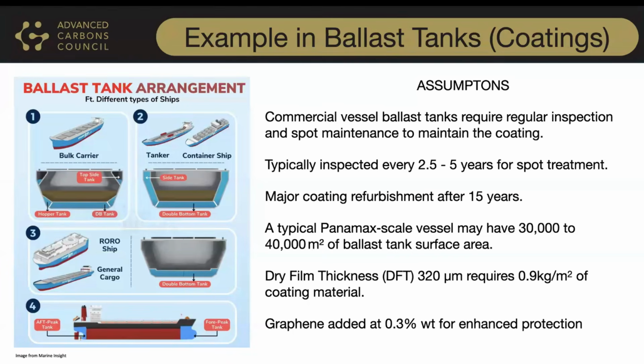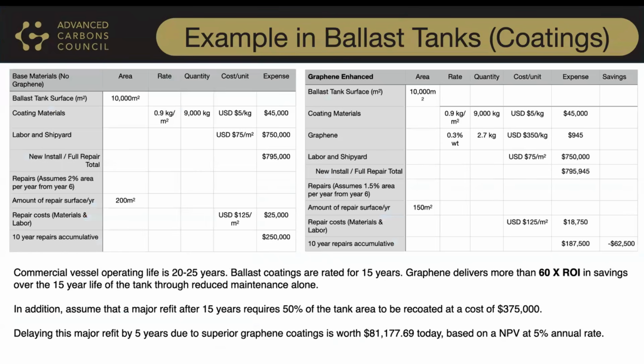And if you have a typical Panamax, and that just means the largest vessel that could go through the Panama Canal prior to the enlargement of the canal, they may have 30,000 to 40,000 square meters of ballast tank surface to be painted. That's per vessel. The thickness of it comes down to 320 microns, and that's about a kilo of coating material per square meter. And for this application, we're assuming an addition of 0.3% of graphene added to the polymer to improve the corrosion reduction. So in these tables, I apologize, they're a little bit small because there's a lot of data to put up. But on the left table, you have the untreated standard approach.